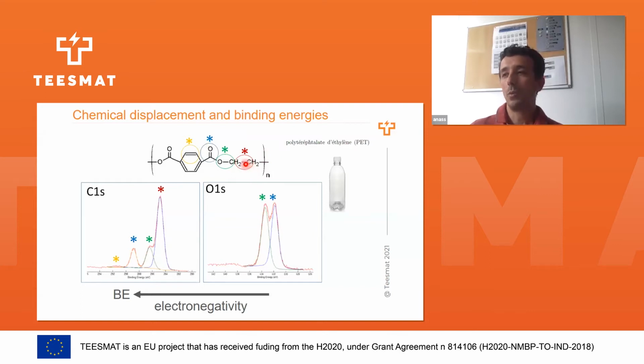And what we can link from the carbon 1s, we have the first peak at lower binding energy corresponding to CH2 bonds. The second peak corresponds to the CH2 bonds to one oxygen. The third peak is the carboxylic group, and the fourth peak is the delocalized electron in the aromatic group. In the oxygen peak, we can see a two-peak signature, one related to the first oxygen and the second related to the second oxygen. So the driving force in this case is the electronegativity.